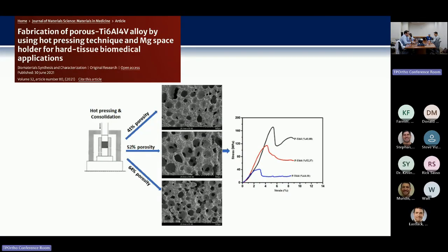It's also really important to understand that historically these stress-strain curves were graphed with solid materials being tested. What's much more relevant to spine surgeons is how newer porous titanium lattice implants behave. There's a recent biomechanical paper published in 2021 about the variance of Young's modulus based on the porosity of titanium. It showed that an increase of porosity decreased Young's modulus, which intuitively makes sense, and again is clinically relevant when determining implants for our patients.